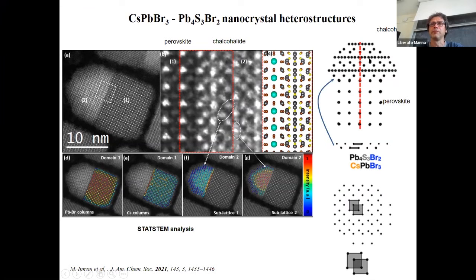So this is the side view, and this is a top view of the heterostructure, looking only at the lead cation framework. And you would see that the lattice of the lead framework of the chalcohalide has this zigzag pattern, and this plane here belongs at the same time to the perovskite and, sorry, to the chalcohalide and to the perovskite.